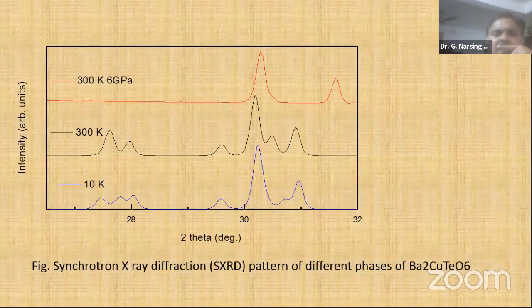I'll just draw it one more time. There is a small range. So you can see this tetragonal one. This is a triclinic one. This is 300 K, room temperature. At low temperature, there is also a phase change in between, but we are studying that once again. So below room temperature there is once again a phase change, because you can see there are 2 peaks here, and here it's 3 peaks.